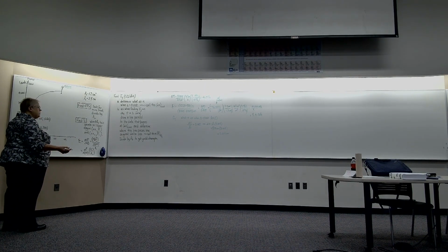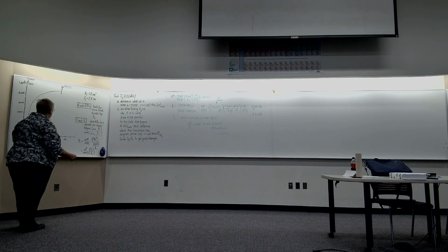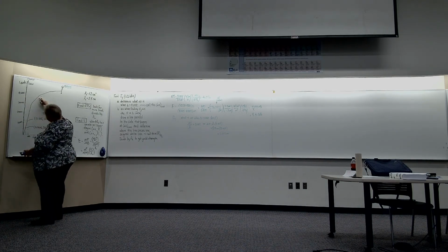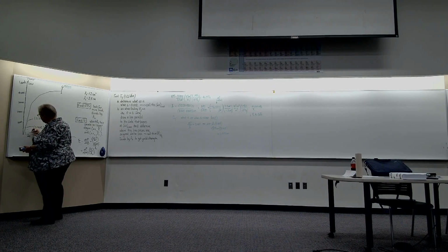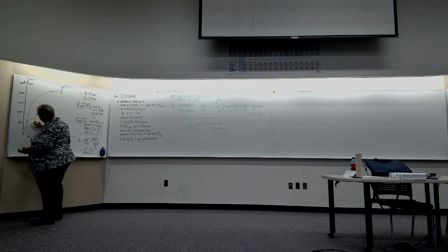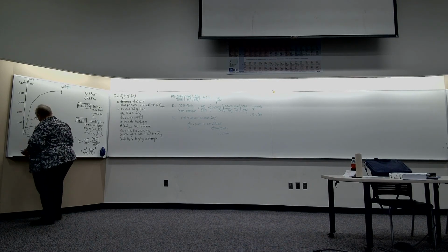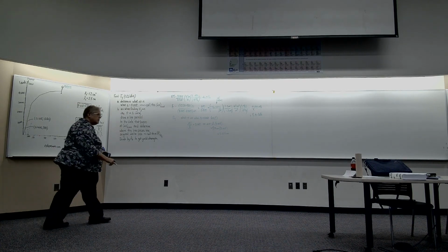And then just like we did with our stress strain curve, we're going to draw a line parallel to the data line that starts where the strain is 0.002, where delta x is such that the strain was 0.002. So that was here. So I just draw a line that's parallel to the beginning of this curve, knowing that the curve won't stay linear.